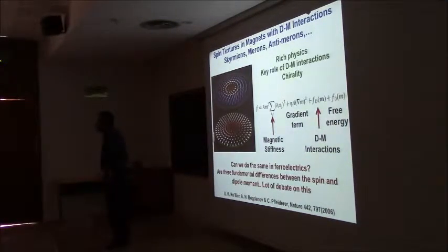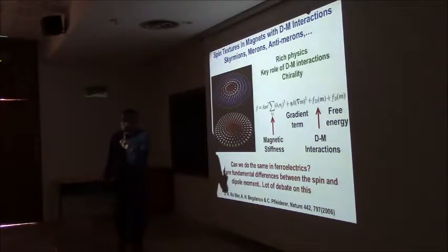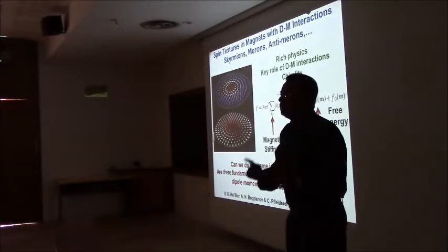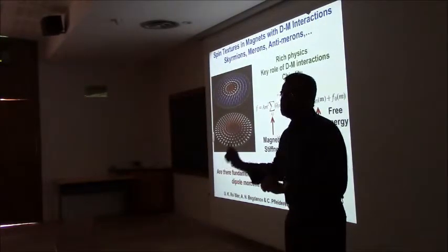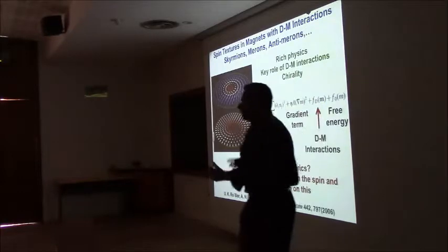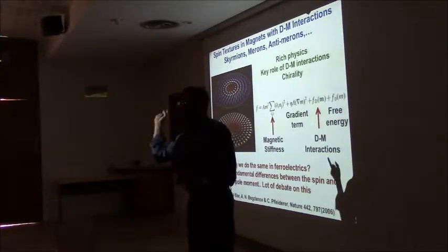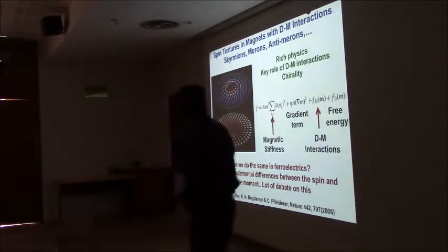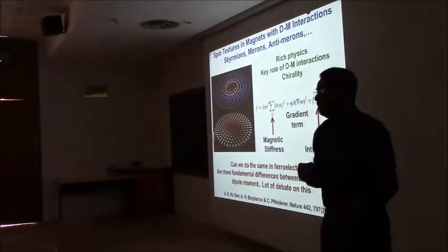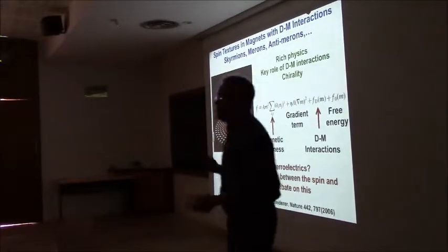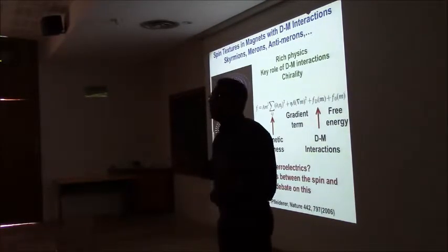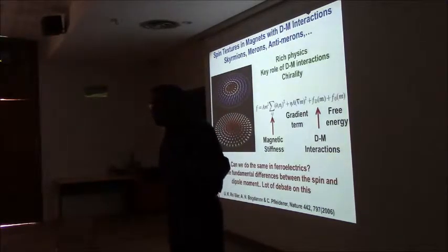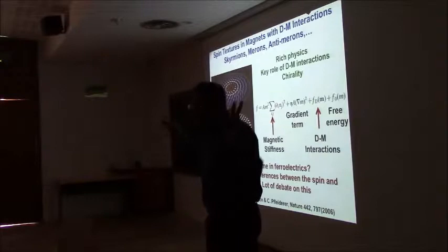In yesterday's discussion, if any of you remember, we talked about bismuth ferrite already being very different. Bismuth ferrite did not switch by the classical Vanderbilt mechanism. Instead, it switched by rotating the polarization in two steps. That's what Jorge pointed out when we wrote that paper. Jorge was the guy who said, guys, it may be very different. And indeed it's true, and we can measure it. Therefore, bismuth ferrite, which has a very large structural anisotropy, still behaves like a ferroelectric.